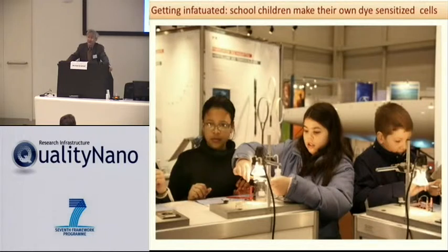Yeah, that's actually some of our Japanese colleagues. They have developed the application in photocatalysis of TiO2 where UV light is used. Well, first of all, I should say the anatase particles we have absorb only light below 380 nanometers, and that's where the cutoff of our tin oxide conducting film is. Tin oxide is also a semiconductor, and the conducting glass we use is a fluorine-doped tin oxide. And so the tin oxide already filters the light, and so does the TiO2 underlayer, blocking layer, that would filter anything that remains. But there's also some other argument that even if the nanoparticles were excited, well, where would the hole go? Of course, to the iodide.